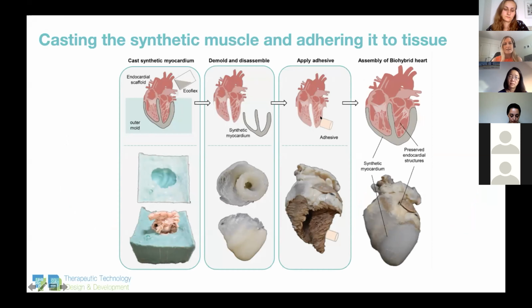Then we had to come up with an adhesive that would work, and this was no easy task, to come up with an adhesive that would adhere fixed tissue to silicone. So we worked with collaborator Professor Xuanhe Zhao, who's at MIT in the Department of Mechanical Engineering. And we came up with an adhesive that worked well for this purpose. So we coated the dissected ventricles with the adhesive, and then put these two parts together. So what we had is this passive biohybrid heart, but as you can see, it looks pretty much like one piece, and we achieved really nice coupling between the synthetic structures and the organic structures.